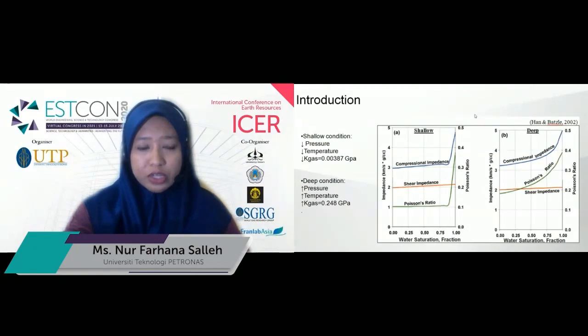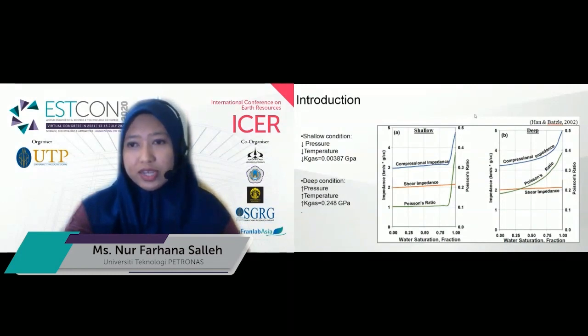So differently to the deep condition, it has a higher pressure and temperature. So the gas trap is having a liquid phase behavior with higher gas modulus, around 0.248 gigapascal. From the right figure, we can see the reduction of rock impedance with increasing gas saturation. It has a more gentle reduction compared to the shallow section.